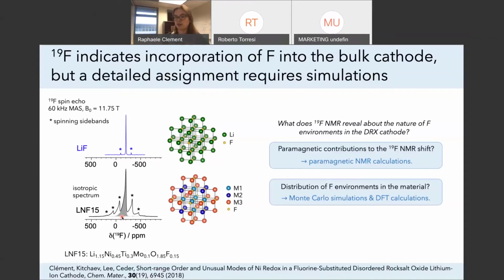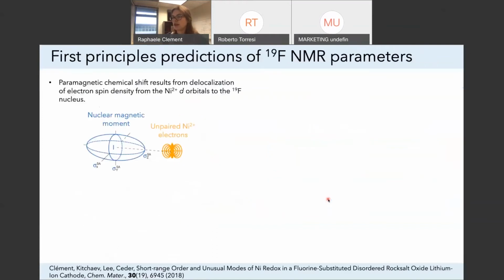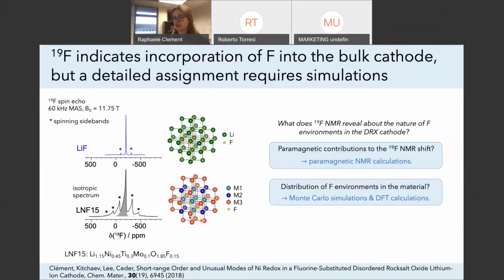But to learn a bit more about these materials, we need to complement our experimental data with first principles calculations. One of them is understanding better the NMR properties of these materials, but also understanding the favorable distribution of fluorine environments in this material. So we carried out this type of analysis for this particular composition shown here.